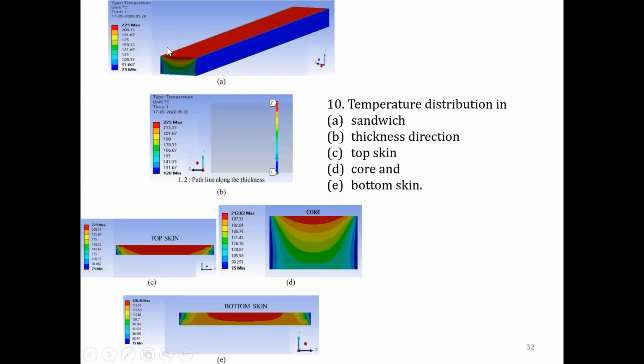So the results of thermal analysis in the form of temperature distribution, as I was talking earlier, are presented in this figure. We wanted to just know how the temperature and stress vary for this multi-material system. It is observed that the temperature distribution varies from skin to core, since a convective heat transfer boundary condition is applied, wherein chamber temperature is set at 75 degrees. The bottom skin is going to have a temperature slightly more than the bed temperature, definitely, because we have a higher printing temperature than the bed temperature. Similarly, the top layer of the skin is subjected to 225 degrees C based on our table and the suitable printing temperature.